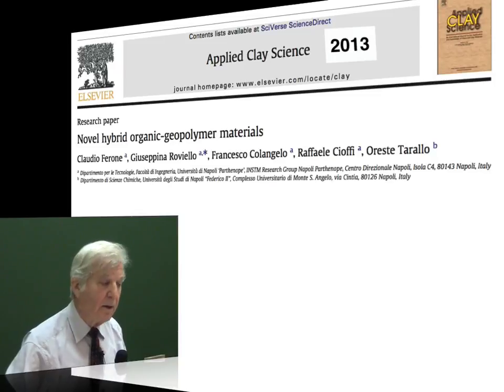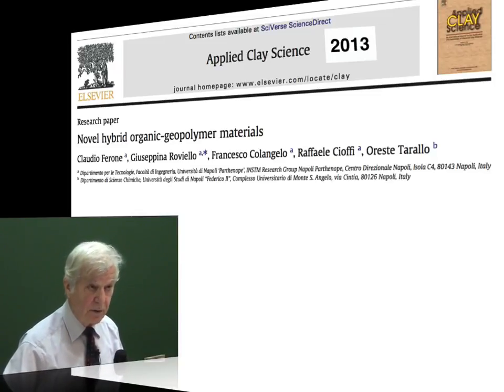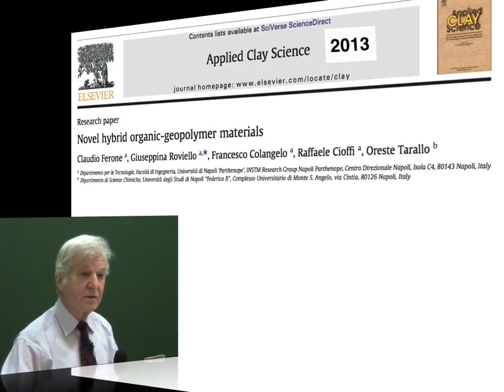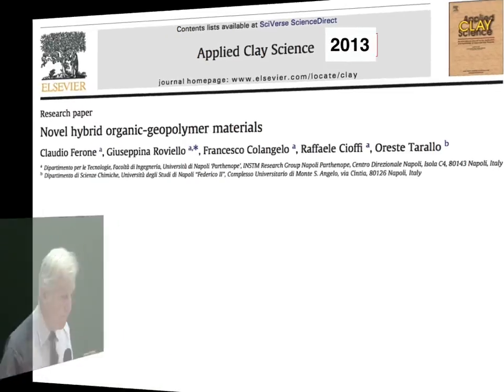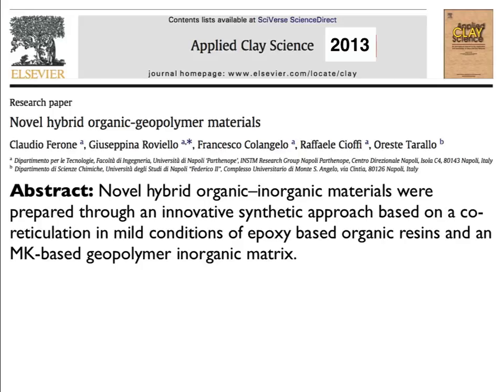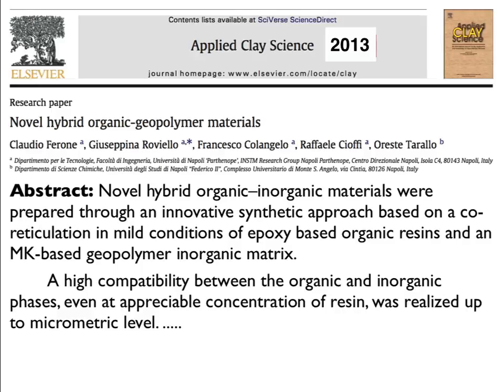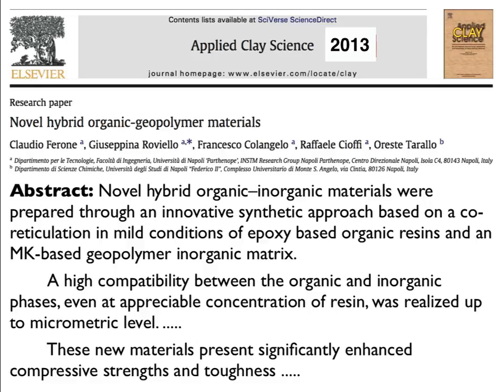How can we increase our knowledge on how to mix these two antagonist chemistries? Well, this is the paper that was published at the same time as the first one. Novel hybrid organic-inorganic materials were prepared through an innovative synthetic approach based on a co-reticulation in mild condition of epoxy-based organic resin and a metakaolin-based geopolymer inorganic matrix. A high compatibility between the organic and inorganic phases, even at appreciable concentration of resin, was realized up to micrometric level. Then these new materials present significantly enhanced compressive strength and toughness.